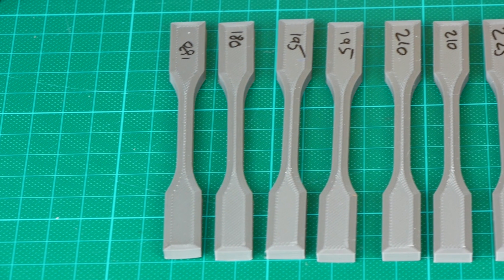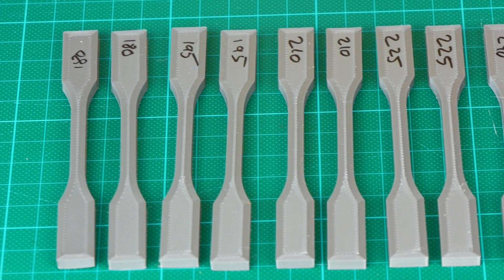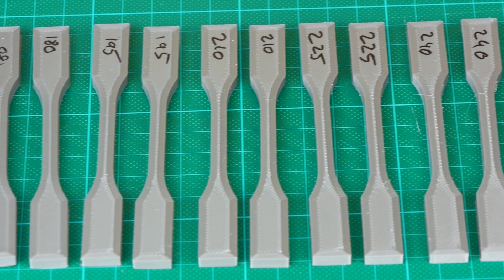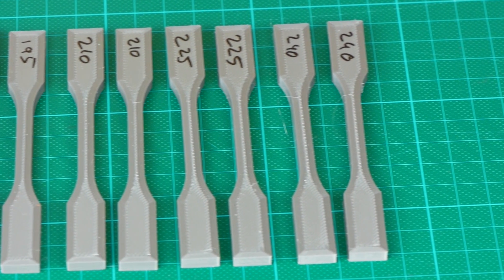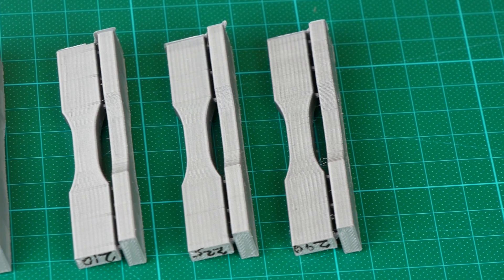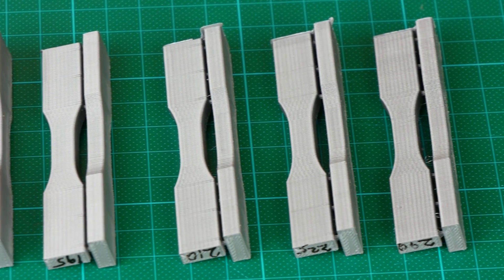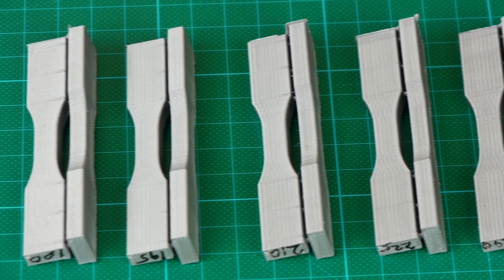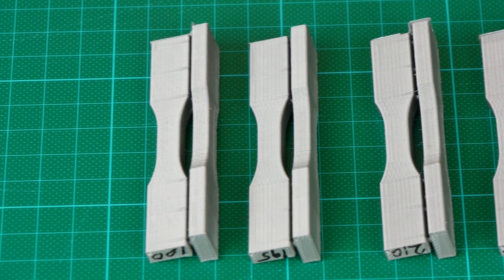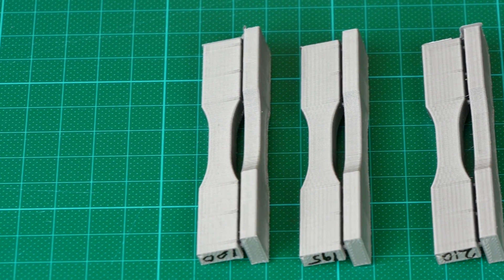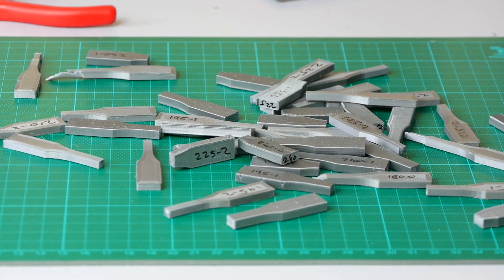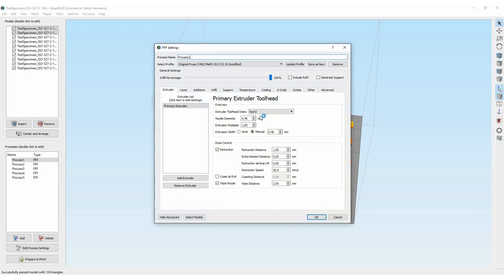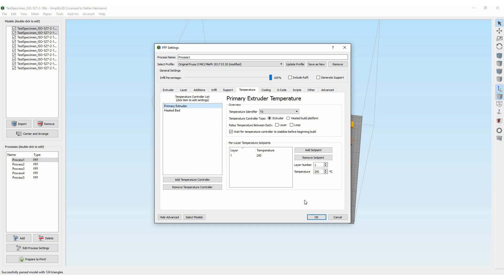For the first print run - I'm going to tell you later why I had to do a second - I used the temperature range from 180 degrees to 270 degrees in 15 degree increments with a 60 degree heated bed. For each temperature I printed two specimens which were lying on the print bed, which tests the bulk material strength, and two upright specimens which gives us information about the layer adhesion. Since I didn't want to create a separate print job for each temperature, I again used Simplify3D's processes.